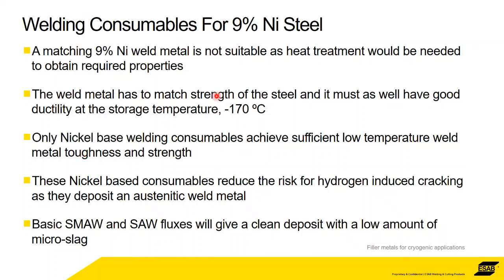So obviously the weld metal has got to match at least the strength of the steel, as well as have good ductility at -170. So it is really only the nickel-based consumables that have that strength and integrity at that low temperature. One other plus point for the nickel-based consumables is they put down an austenitic weld metal. So again, there's reduced risk of hydrogen cracking, whereas we're increasing the risk of hot cracking. There's a reduced risk of hydrogen cracking because it's austenitic and not ferritic.